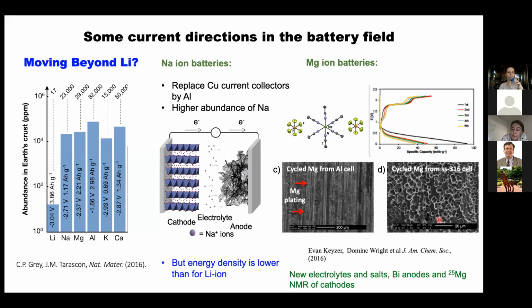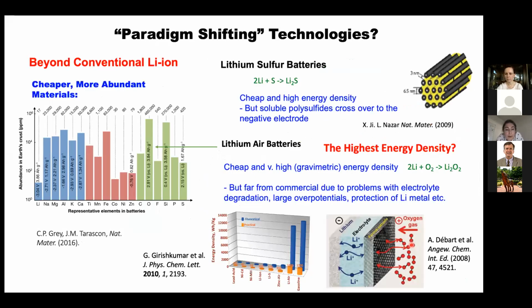But the other reason why people like magnesium is that you don't form these dendrites under reasonable rates. So this is an example of, instead of the dendritic structures you get in lithium that I'll show you more of later, you get these globules, and that's another attraction for magnesium. But it's an area of work in my group, but it's one where there are tremendous challenges to get that to be commercial. And so what about the paradigm shifting technologies?